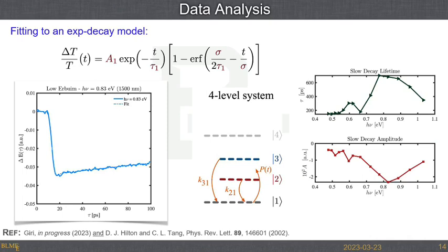This 0.8 eV corresponds to where Joshua thought these erbium arsenide nanoislands should be. So our experimental data actually backed up some of the modeling that he had been doing, which I can't emphasize enough, never really happens. Usually the numerical modeling is a good approximation, but you're off by a factor of 2 pi, because that's just the way physics works sometimes.